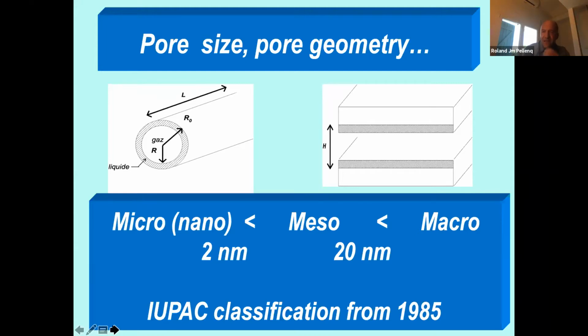The reason for that, and there is a physical reason, is that when the confinement becomes so strong, it kills any phase transition of the fluid. The fluid structure in the porous material is then entirely due to the interaction with the solid. When we're in the meso range, we do still maintain some kind of phase transition, such as the capillary phase transition.